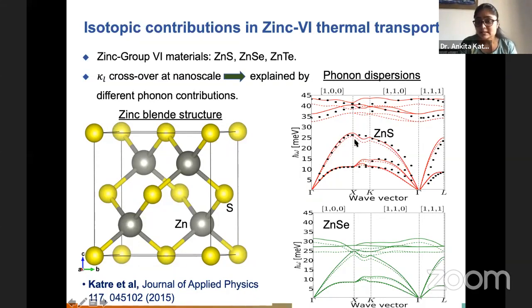So we see that there is a huge acoustic-optic phonon gap here, which affects the phonon-phonon scattering in these materials. If you have a bigger gap, the scattering would be smaller. That's the simplest explanation I can give you as of now, which you will figure out when you see the formulation as well. For the case of zinc selenide, we don't see this acoustic-optic gap here.